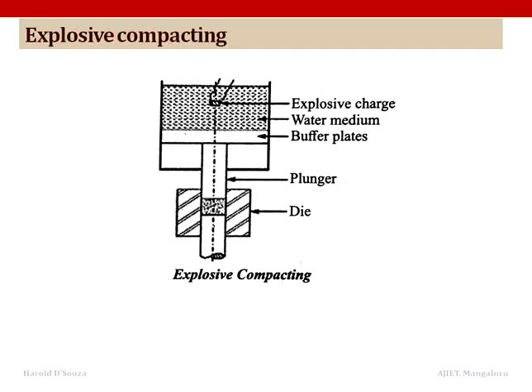Explosive compacting. In this method, the pressure generated by an explosive is used to compact the metal powder. Metal powder is placed in waterproof bags which are immersed in a water container cylinder of high wall thickness. Due to the sudden detonation of the charge at the end of the cylinder, the pressure in the cylinder increases. Now this pressure is used to press the metal powder to form the green compact.